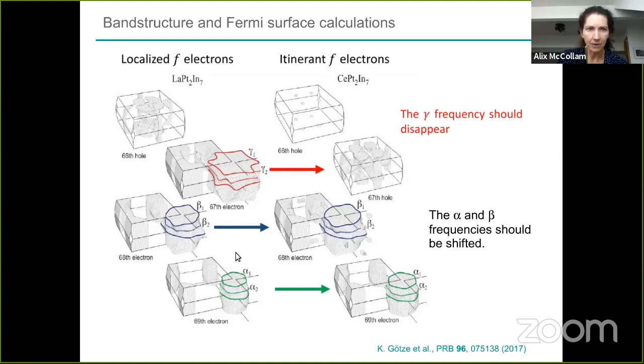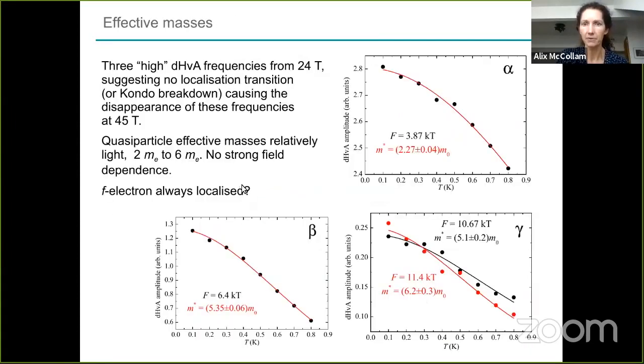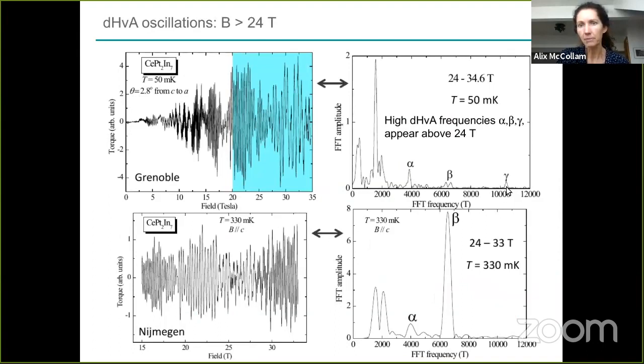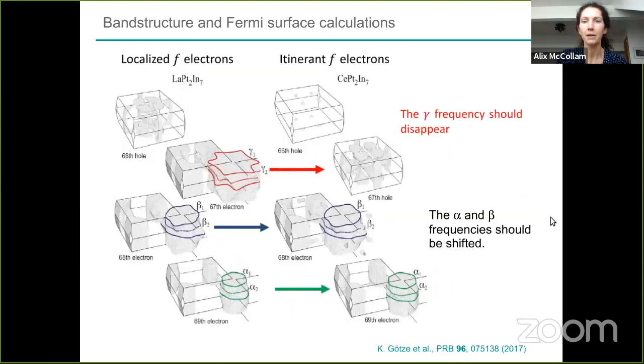They look rather similar and the picture didn't come out so well, but this is basically what you need to pay attention to: if you have a transition from localized to itinerant f-electrons, the gamma frequency should disappear. So that's this one here. And then the gamma frequency is this small one. But even though it's small, this one is just really big. So it's still quite well resolved and we could measure it very well. And also the frequencies of the alpha and beta oscillations should shift.